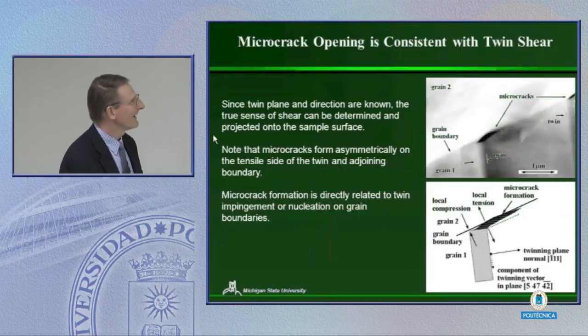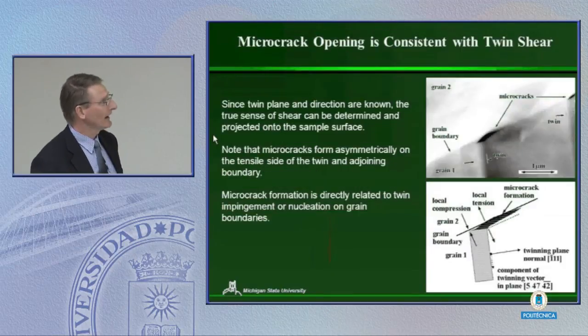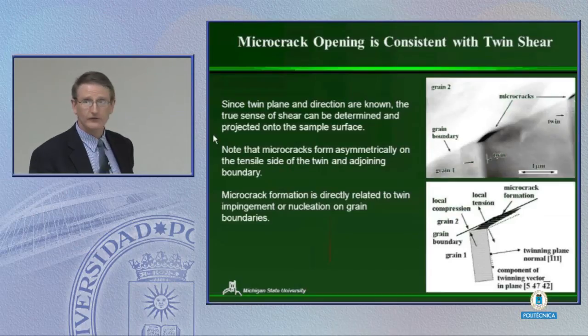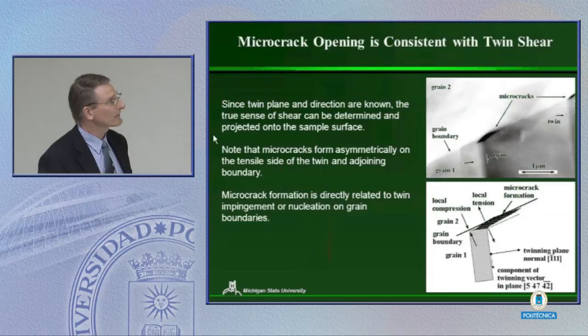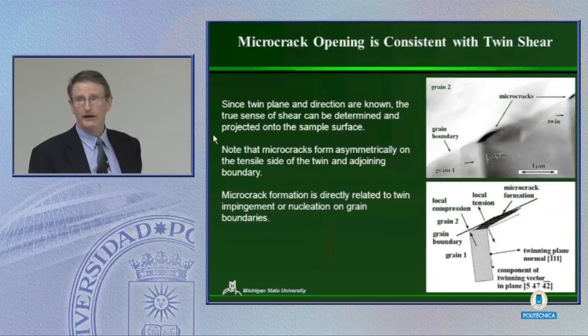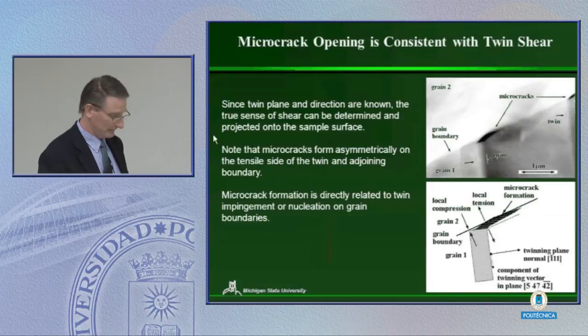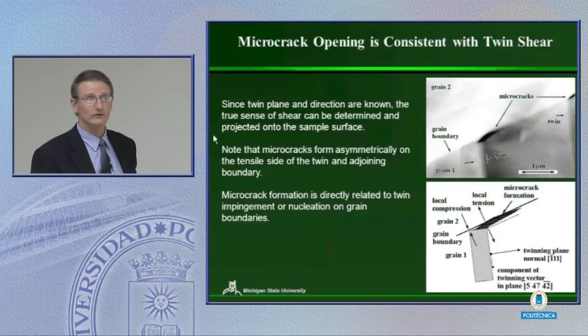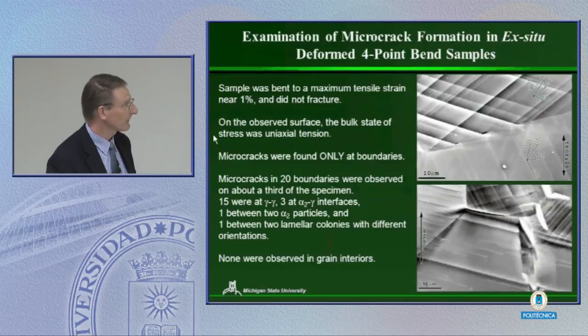Okay? And if we do the crystallographic analysis on this, again, we know the exact nature of those twins. So we know twinning is unidirectional, and so we know we'll have a specific shear associated with a twin. And we find that these microcracks are located asymmetrically in relation to the twins. And that asymmetric nature is completely consistent with the shear that we expect from those twins as they open up. And so we're very confident that the microcracks form as a direct consequence of the twins nucleating at that boundary there.